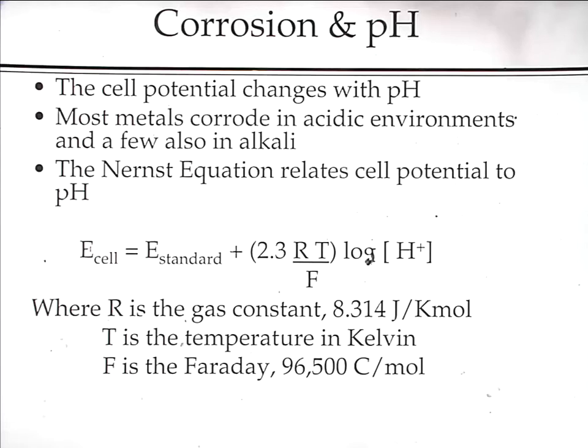So we tend to think that acidity enhances corrosion. That's certainly true for iron, for steels, but quite a lot of materials get attacked in alkali, aluminium alloys particularly, and at high alkali values, stainless steels are also sensitive to attack in alkali. So there are risks at high alkalinity, and there are risks at high acidity for a variety of alloys.